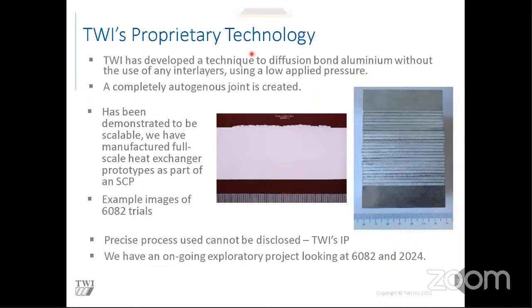Compared to other solid state welding processes, how much is the joint strength, as far as similar material systems like Al-Ti go - so what is the joint strength? For a lot of the diffusion bonded joints, the diffusion bonded joint can be the weakest part, but it's not always the case. Like the example I showed earlier, it actually failed in the parent material. We like to get to around 90% of parent material strength or higher. So whilst they might be slightly lower strength, if you've done the process properly and removed all your voids, they're as good as the parent material. So they shouldn't create any sort of failure concerns specifically.